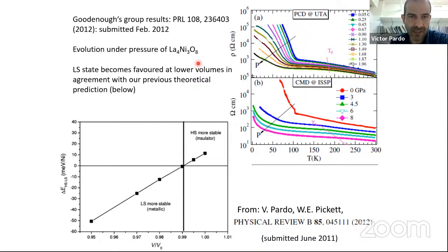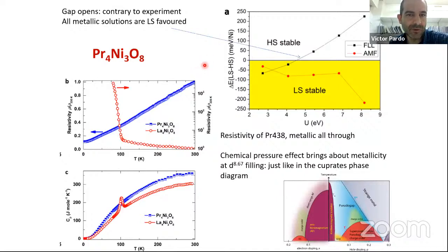So we thought, okay, there has to be some other way to produce a metal, and we substituted lanthanum by praseodymium. Praseodymium is smaller than lanthanum, and well, what we thought was, okay, this would bring the system closer to a metallic solution. And our calculations say about the spin state of the nickel in this structure of the praseodymium 4 nickel 3 O 8 that indeed it is low spin.